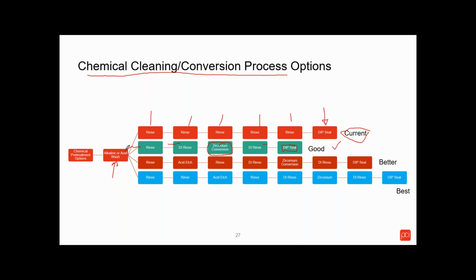And now we diverge and go from an acid wash that does all the etching to an alkaline wash for the next two options. We go to an alkaline wash because that's specifically designed just to remove organic soils. That happens first, and we go through a rinse. But now we still need an acid etch to remove those oxides on aluminum substrates. So that's a separate step in this case.